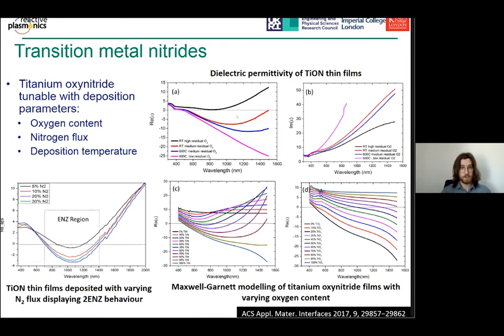Whether we were introducing oxygen, for example here, or as a residual oxygen partial pressure in the deposition chamber. So by controlling this residual partial pressure and the deposition parameters, for example, temperature, we've shown that we can tune from metallic behavior to double epsilon near zero behavior to fully dielectric behavior in these titanium oxynitride thin films. And the mechanism of this tunability is confirmed using Maxwell-Garnett theory, where we show that by changing the oxygen inclusions within an effective medium, we can shift from this metallic to double epsilon near zero behavior.